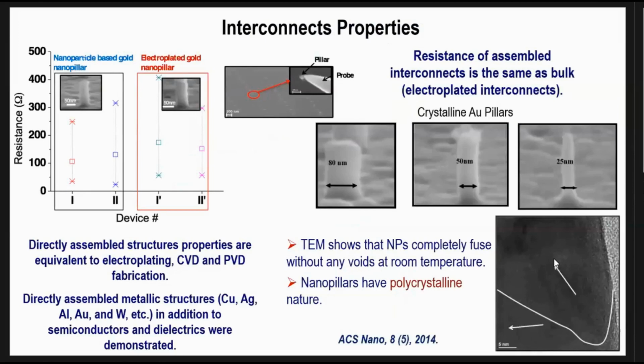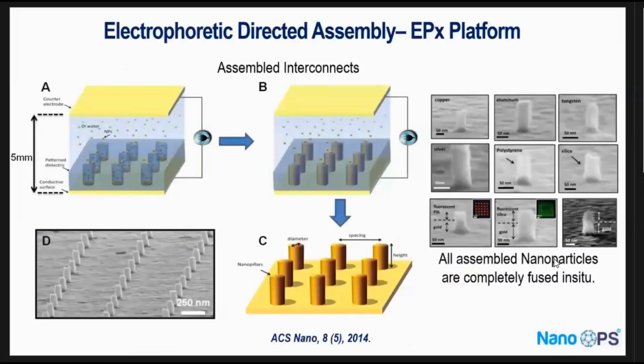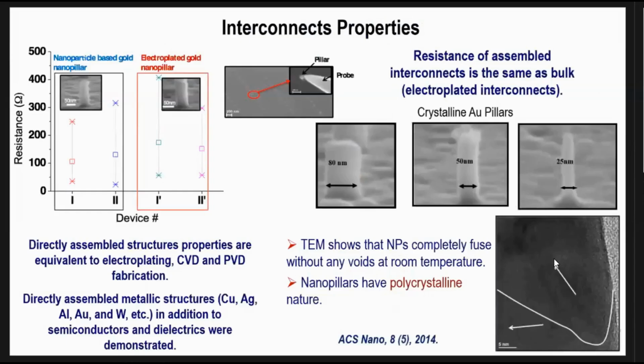By the way, for this particular one, sintering is not needed because the particles are small enough, the surface forces are large, and as a result, the sintering happens in situ. By the time you finish assembly, it's all sintered. So the question was, is it completely a solid film? Do we have any voids? Is it amorphous? Is it polycrystalline? And so we looked at that issue.